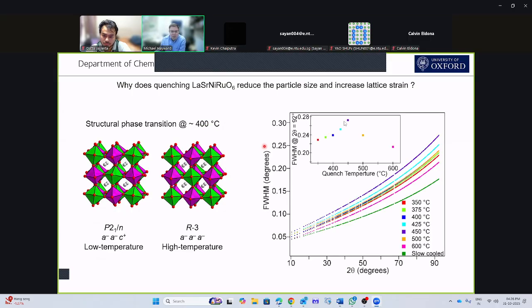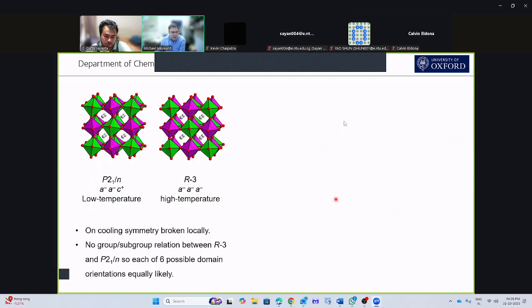And what we find is if we slow cool samples to various temperatures and then quench them from those temperatures, we see that quenching from just above this transition temperature gives us the broadest peaks in the diffraction pattern. So that gives us the most strained and smallest particle size samples. So why does quenching do this? Well, what we see is that on cooling, we'll go from this phase, this R3 bar phase, to this P21/n monoclinic phase.